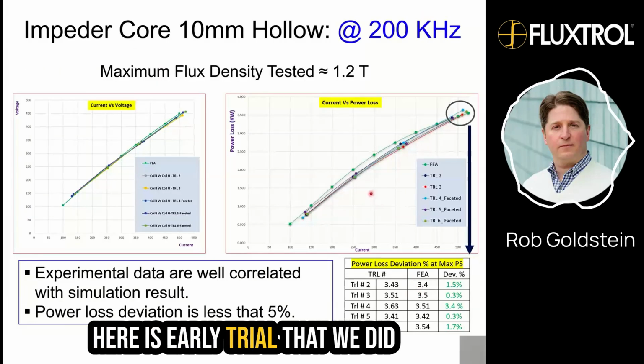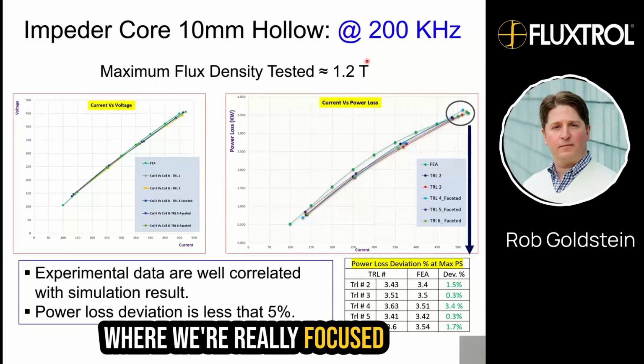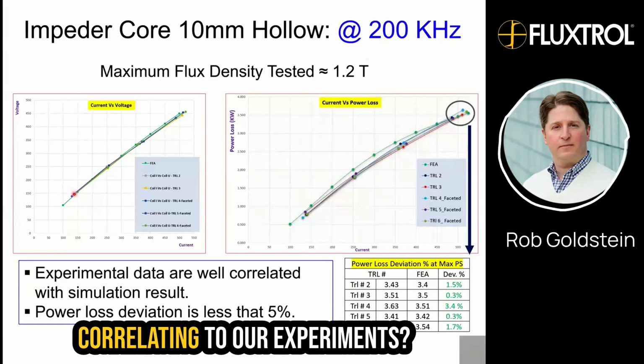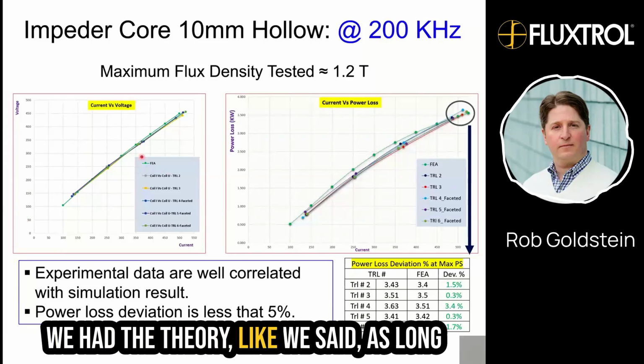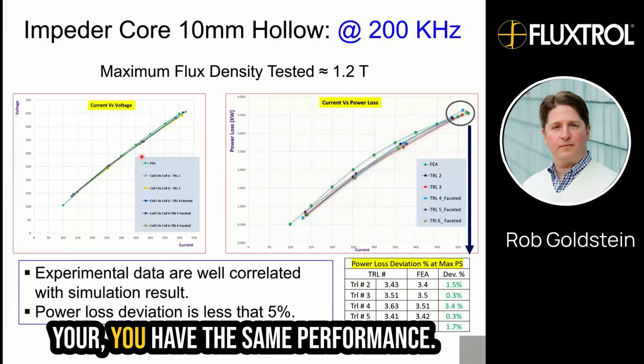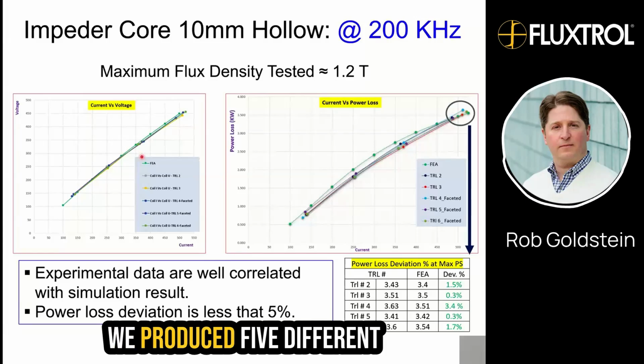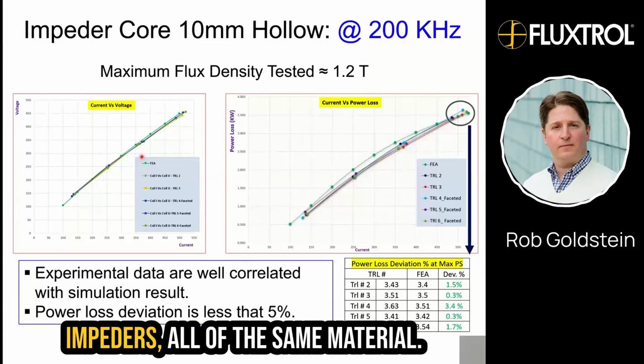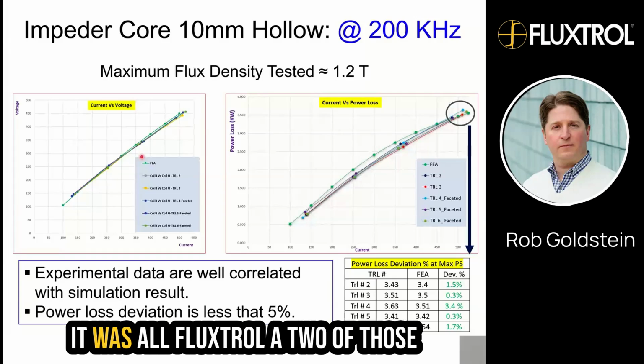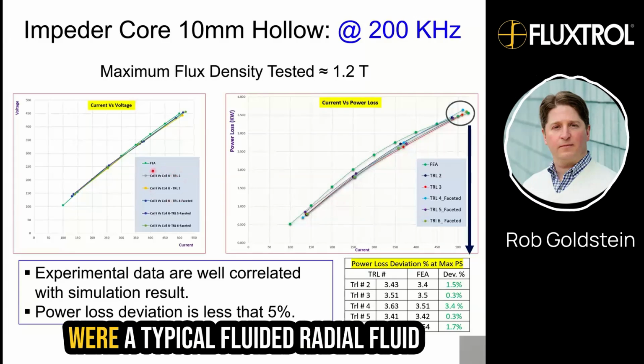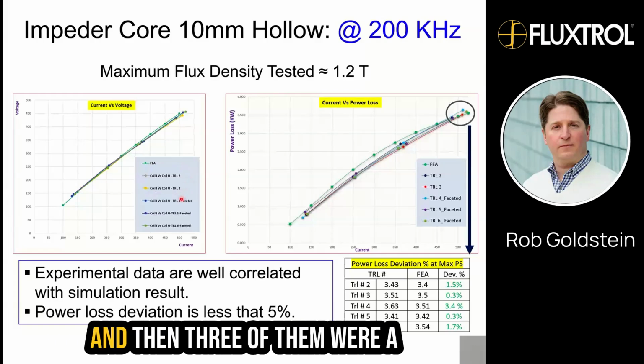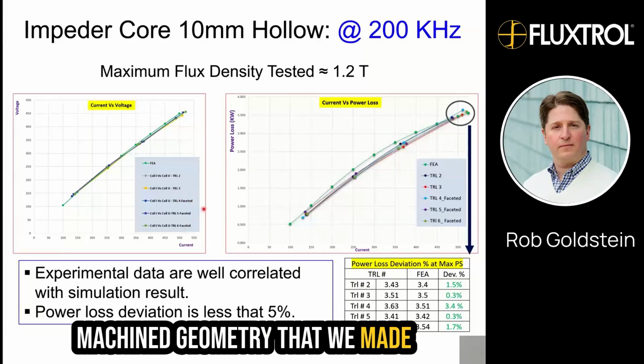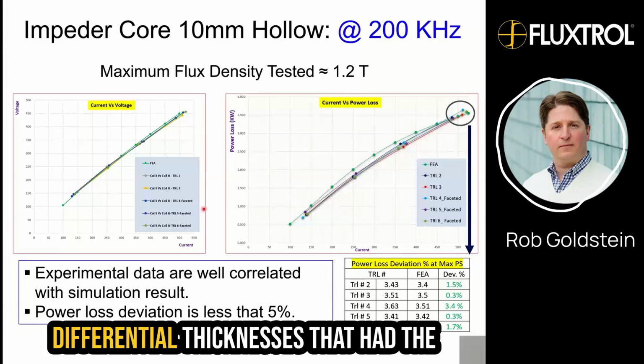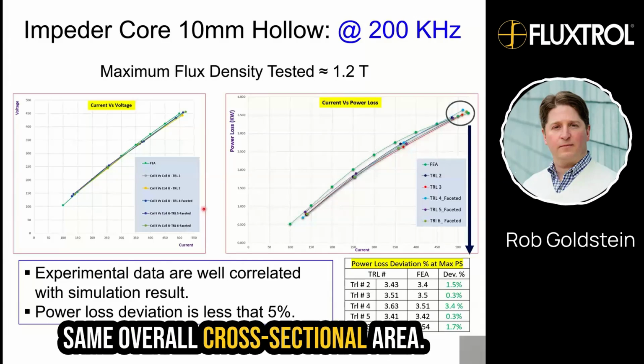Here is an early trial that we did where we're really focused on, okay, how are our models correlating to our experiments? We had the theory, like we said, that as long as you have the same cross-section, you have the same performance. We produced 5 different impeders, all of the same material. It was all Fluxtrol A. 2 of those were a typical fluted, radial design like ferrites are used. And then 3 of them were a machined geometry that we made called faceted, with flat faces with differential thicknesses that had the same overall cross-sectional area.